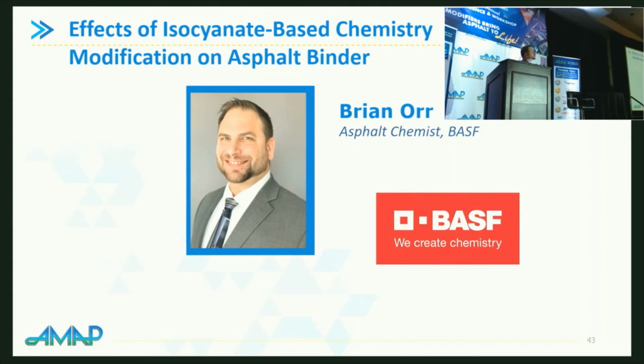Hello. I was wondering if you had any elastic recovery numbers with just the isocyanate as an additive. I do. So again, like I said, you don't get much elastomeric properties. It's not an elastomer. It's more like my rubber ball here. If I throw this against the wall or something and you record it on a slow motion camera, you can see it smash and completely recover, right? However, it's not like a rubber band. You cut it, you damage it, it doesn't come back, okay? So you can get probably, I've seen a 10 to 15% recovery with it by itself.